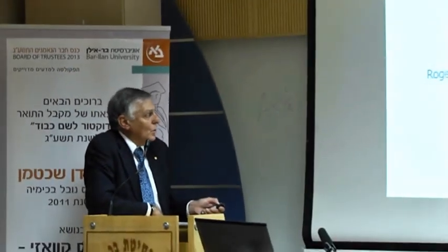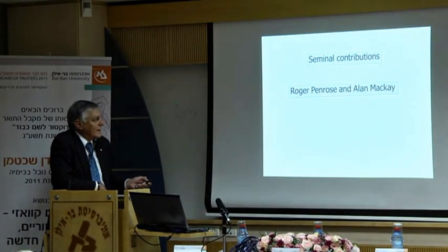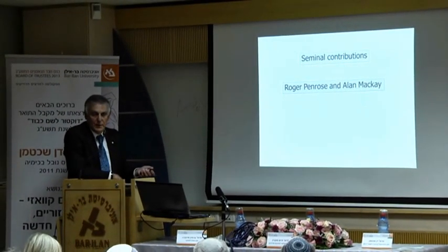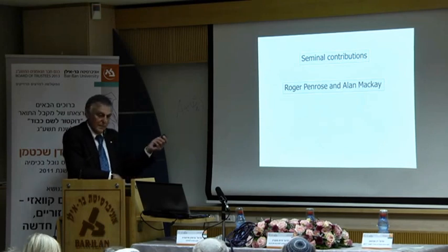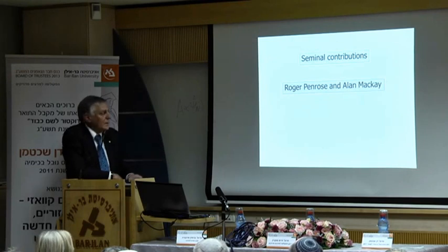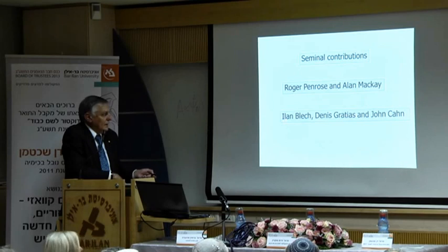I mentioned Roger Penrose. Alan Mackay is a very famous and good British mathematician. He took Roger Penrose's tiles and showed that they diffract, giving sharp diffraction spots. You can do it by Fourier transform on the computer. Nowadays you can do it by simulations, or simply by optical diffraction using a laser beam. That's Alan Mackay.